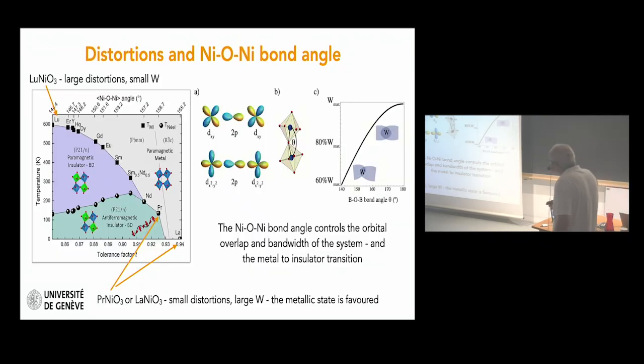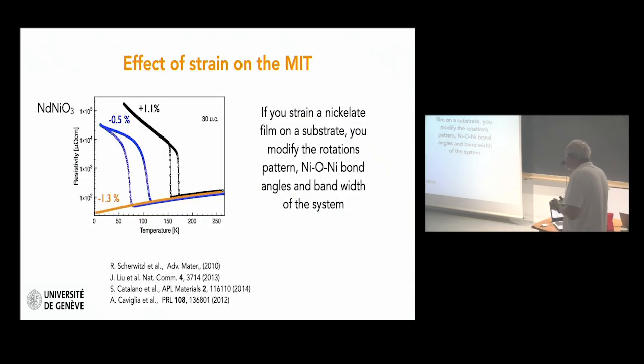And this is what I just mentioned before. When you go down in size, you change the nickel-oxygen-nickel bond angle. By doing so, this is what you see here, you change the overlap of the orbitals, you reduce the bandwidth of the system, and the system turns insulating at higher and higher temperature. This can be used in thin films. One can use strain in thin films to change these rotation angles and affect the metal to insulator transition.